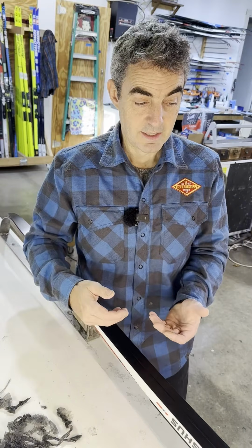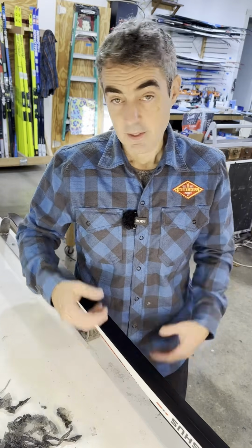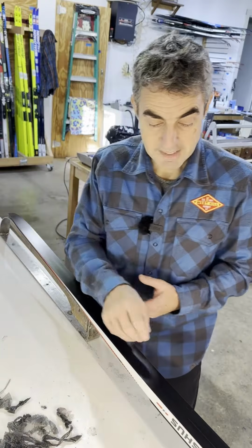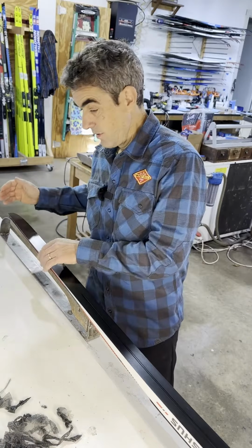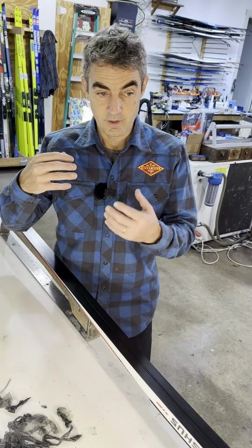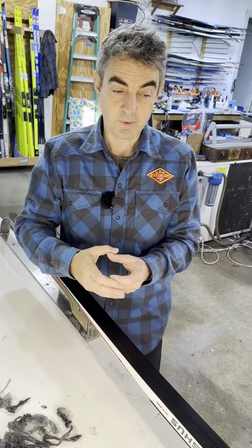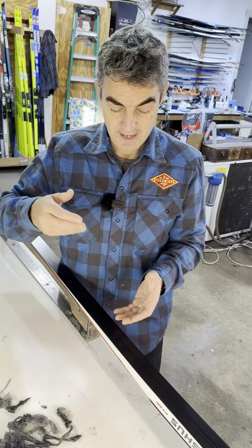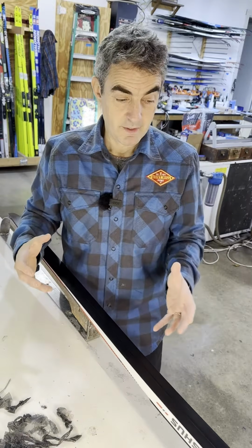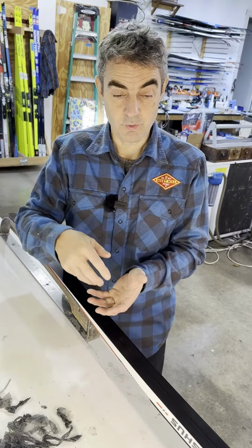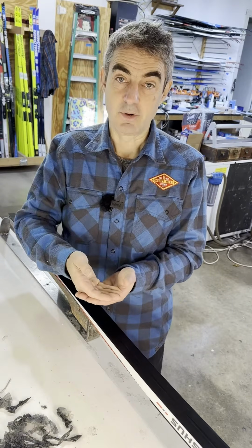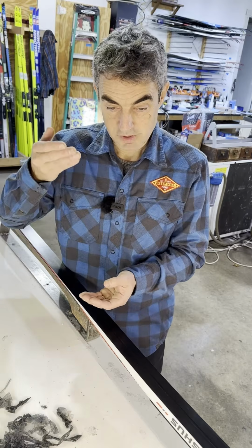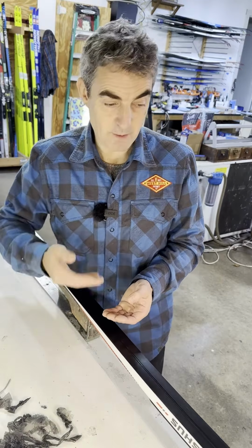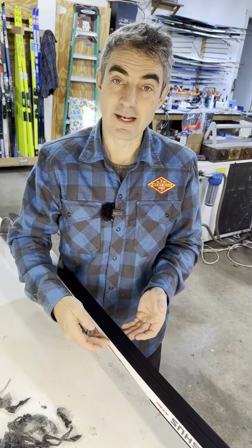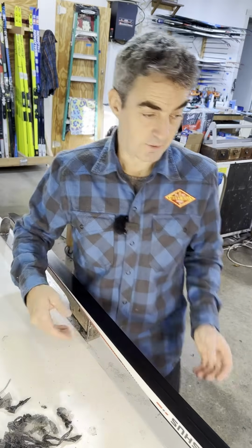So there's a really profound implication here with respect to the way we're going to iron. The process is rapid, almost immediate. When we apply heat that yields the wax into an optimally fluid state, and we have the base excited and opened up, then the wax penetrates to the depth of that temperature gradient. And so we can push that temperature gradient down as far as we're comfortable without trying to heat all the way through.